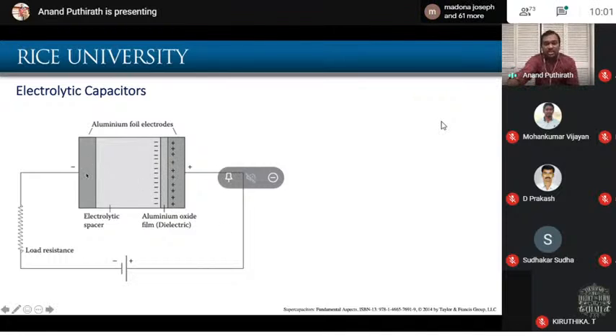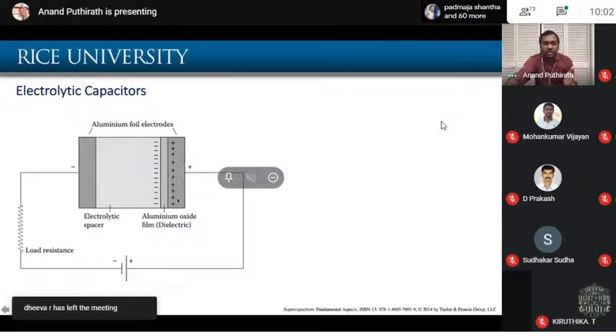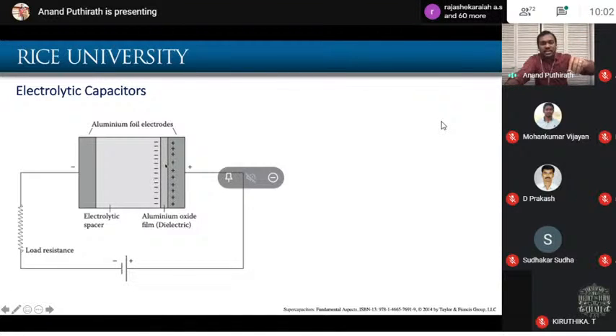Here you have still two electrodes, but what we have done is you have an electrolyte in this system. So basically, you will take polished aluminum, for example, on one side, and cast aluminum on the other side, and you put some electrolyte into the system. So this electrolyte, when it interacts with the polished aluminum surface, will produce a small, thin layer of oxide across it, which is our dielectric now, which is of the order of a few micrometers or below.